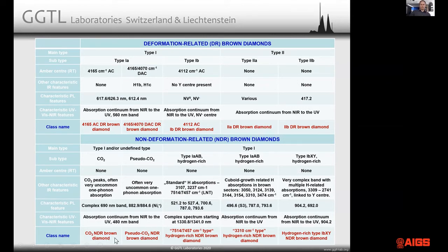So this gives a total of 10 different classes of diamonds, and you can fit pretty much any brown diamond out there in this scheme without any problem. The only ones that might be a limit sometimes is if you have an orange-brown stone with a strong green fluorescence. You might, in certain cases, not find an amber center in them, but that's really the only exception to the rule. The rest will certainly fit in every single one of these proposed classes.